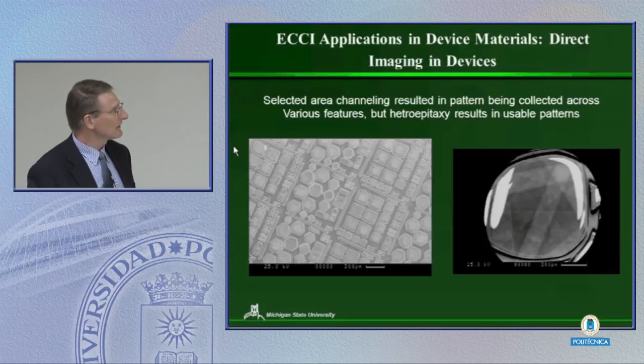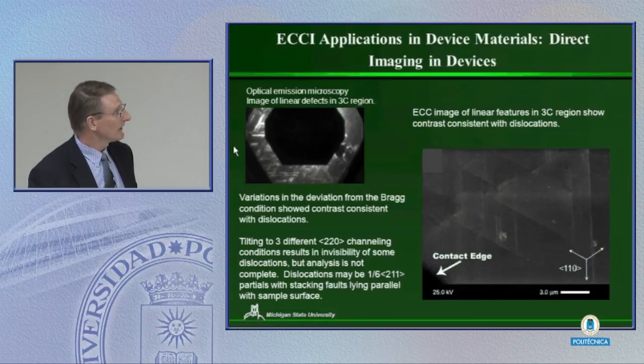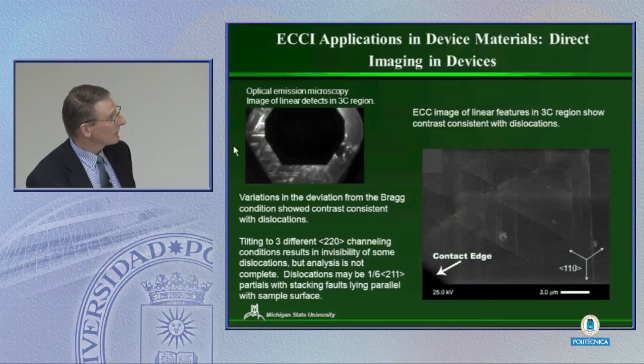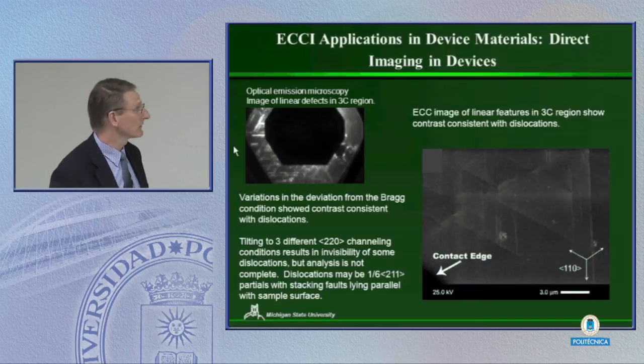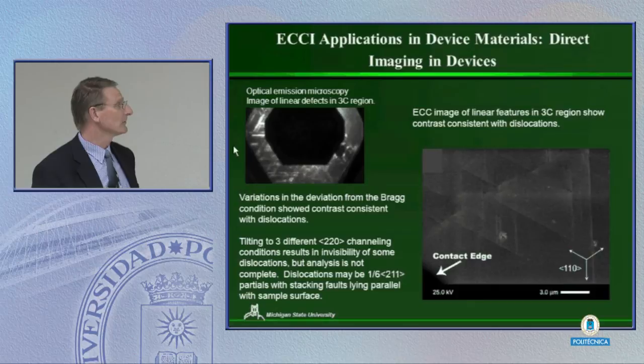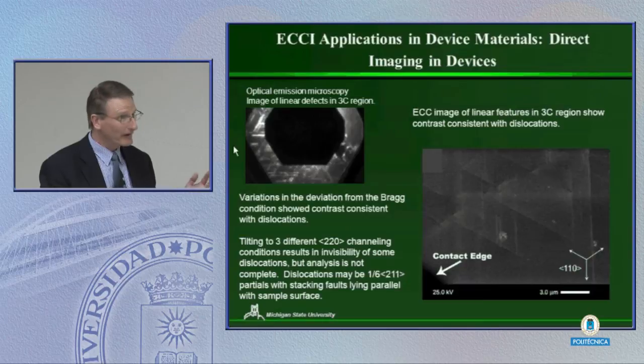But the reality is that this is a heteroepitaxial situation, and this is in exactly the same orientation as this, and this is in exactly the same orientation as this. And so it makes it actually pretty easy to get a channeling pattern. We certainly get an interference from the various structures on there, but we can get the pattern really without any difficulty. And looking at that, this is what they had looked at with their optical emission microscopy. This is now in one of these areas here where we see exactly the same sorts of structures, obviously much better resolution. We did some tilting experiments and we were able to get some of the dislocations to go out of contrast, which helps confirm to us that these really are dislocations.